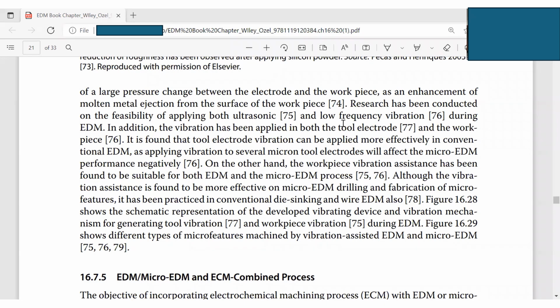So we can use both ultrasonic and low frequency vibration during EDM. The vibration can be applied to the tool electrode, or you can vibrate the workpiece. It is found that tool electrode vibration can be applied more efficiently in conventional EDM, as applying vibration to several micron tool electrodes will affect micro EDM performance negatively. On the other hand, workpiece vibration assistance has been found to be suitable for both EDM and micro EDM. Although vibration assistance is found to be more effective in micro EDM and the fabrication of micro features, it has been practiced in conventional die sinking and wire EDM also.